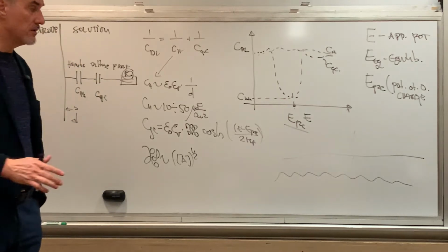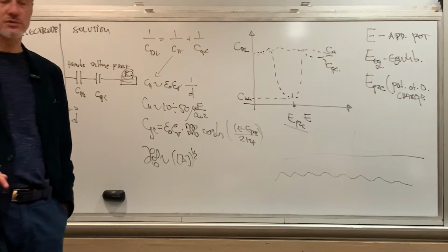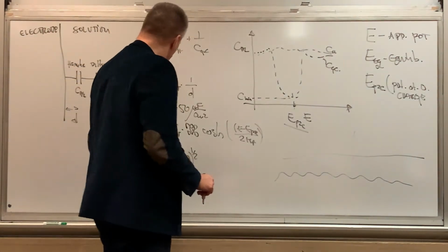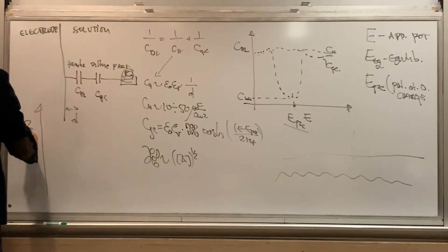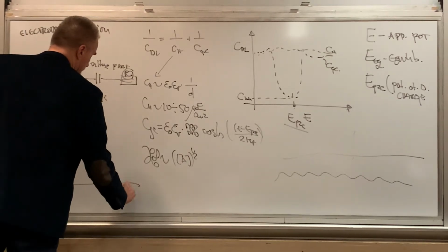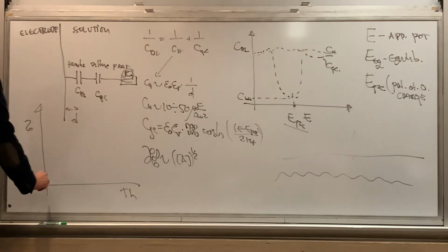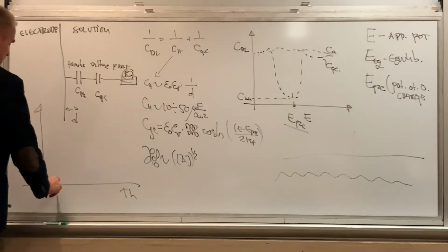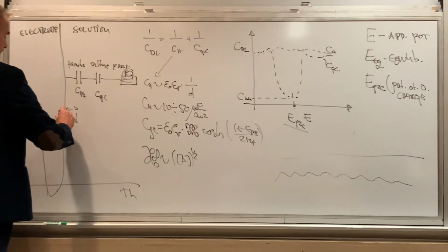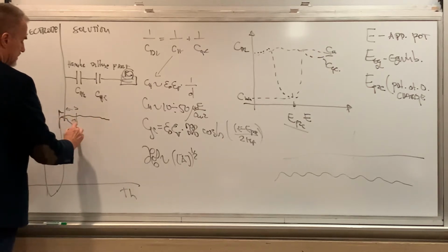Also, one of the key issues when you have thin films in general, with any kind of deposition, is that if you look at the stress as a function of thickness curve, usually it starts with a small compressive stress due to nucleation, then there's a huge tensile rise, and then the stress either stays constant or starts to decay.